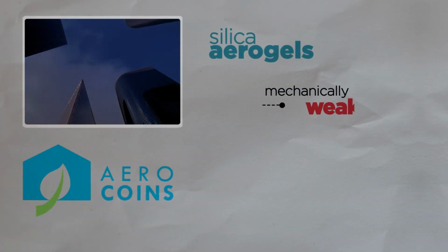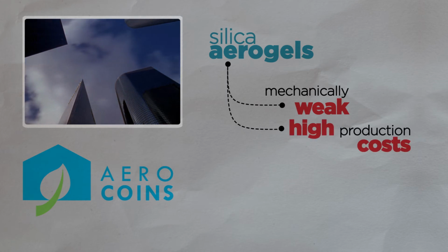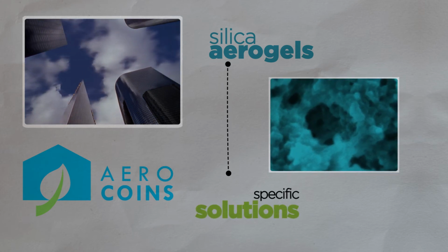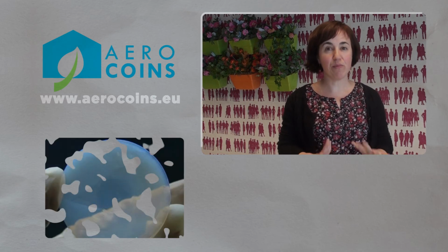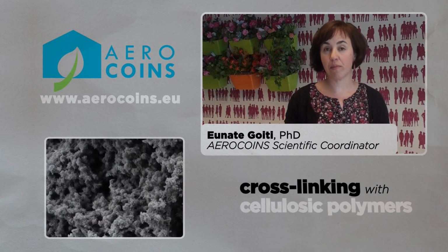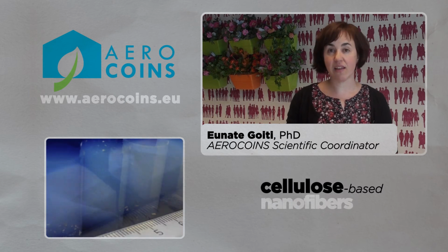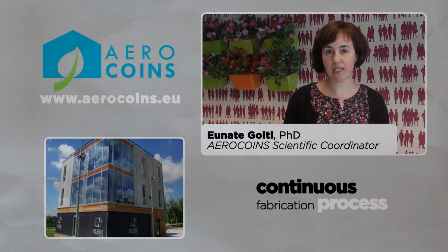At the moment, silica aerogels are mechanically weak and require high production costs. These are 2 major obstacles that have prevented a widespread use of silica aerogel insulation components in the building industry. AeroCoins offers specific solutions to these issues. At AeroCoins, we are developing new methods for strengthening silica aerogels using cross-linking with cellulosic polymers or by incorporation of cellulose-based nanofibers. In addition, we are promoting ambient drying and a continuous fabrication process.